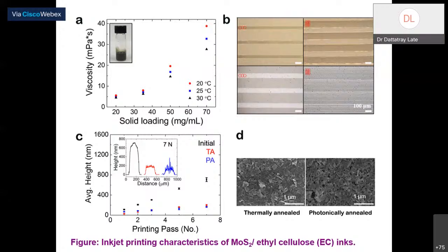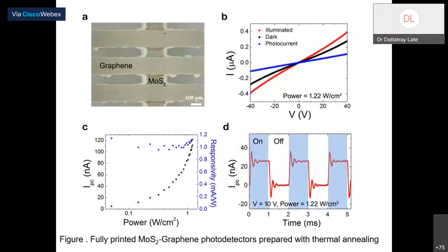For example, how much is the thickness? Just putting the initial coating of the layer. Then we have thermally annealed the device. We have photonically annealed the device, and checked how much is the thickness and all these things, right? Once we have annealed the device, the thickness becomes stable, and then we have done this experiment. You see how the surface slightly changes when you have done thermal annealing or photonic annealing and all these things. Once your device is ready, you can go for device performance or device testing.